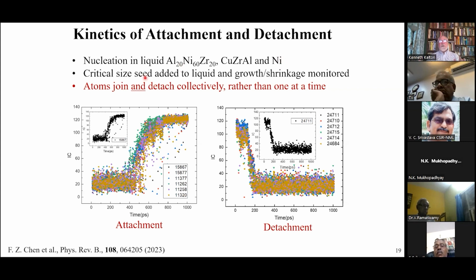So you add this critical seed, and then you watch the shrinkage and growth. And what you find out, I'll show you this in a second, is that atoms don't just attach one at a time. They attach and detach collectively. So more than one atom. Here's an illustration. Here's a case, this is an MD simulation showing the change in index of crystallinity as a function of time.